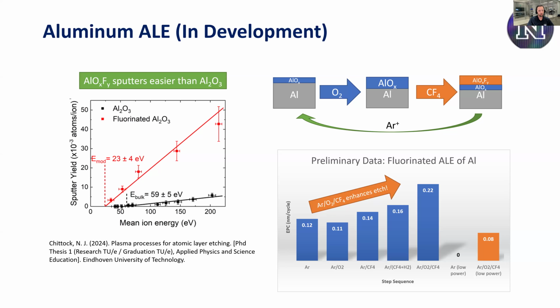In these initial experiments, it turns out our ICP power was too high. But if you just do the oxygen step, just the physical etch, or just CF4, they're all kind of the same within error. We also tried CF4 with hydrogen, because we thought maybe there's an HF-type effect, or that we didn't want too much fluorine. It went up a little bit, but not that much, possibly because there was an undersupply of fluorine radicals. When we got rid of the hydrogen and used this argon, oxygen, CF4 process, we saw a pretty significant enhancement in the etch per cycle.